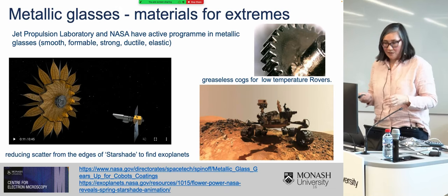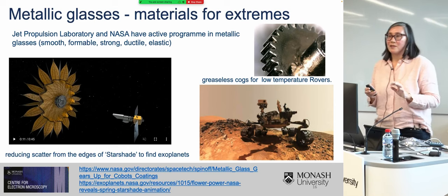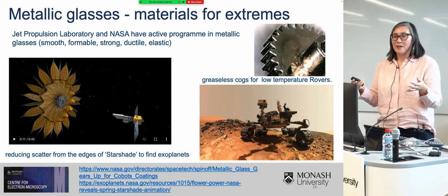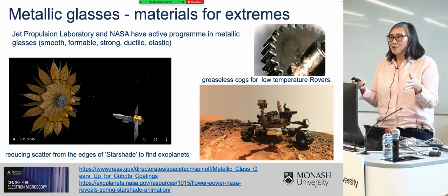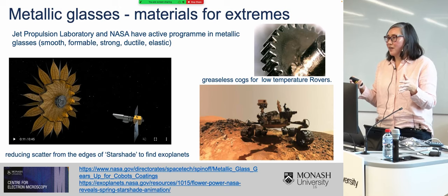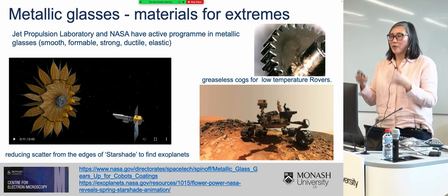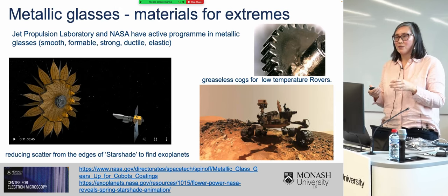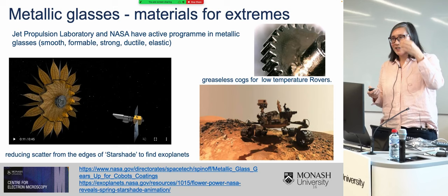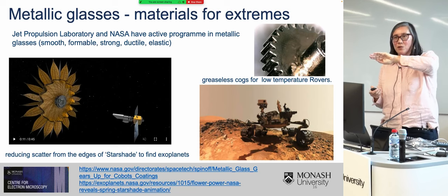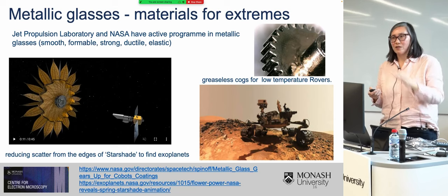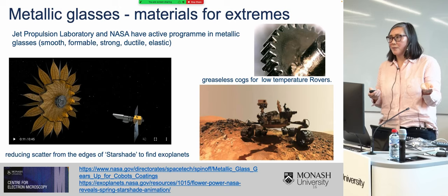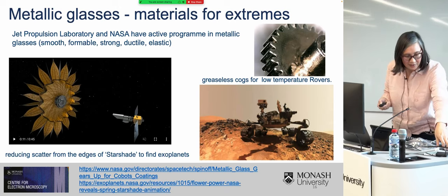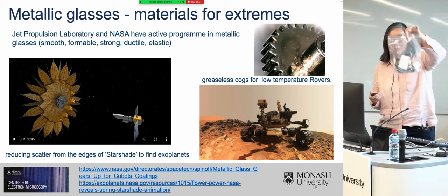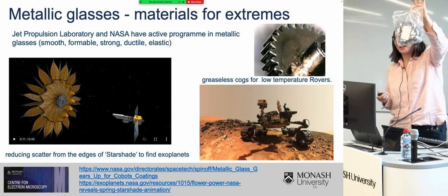And I mean, these are materials that really don't want to be a glass. So, you know, metals form close packed crystal structures. They really don't want to be a glass. And so when you form them, you have to form them quite violently. So by quenching them quickly, and usually this involves injecting a melt onto a cooled spinning copper wheel, which is going at about 1,000 RPM. And if you do this, as my collaborator at CSIRO does, then you obtain little ribbons like this.